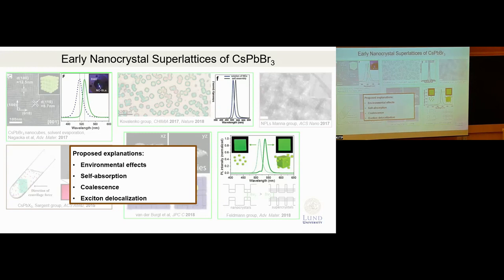For example, a shift in photoluminescence. It's a red shift. When you go from the solution of nanocrystals to the superlattice, you see that the emission wavelength becomes longer in the superlattice as compared to the solution. Several explanations have been proposed for that. One was the environmental effect, so you change your dielectric constant when you go from the solvent, a low dielectric constant, to the film, a high dielectric constant. And that is known to affect exciton energy.